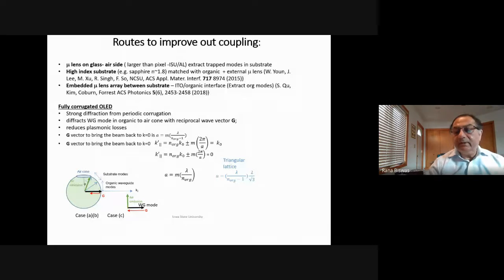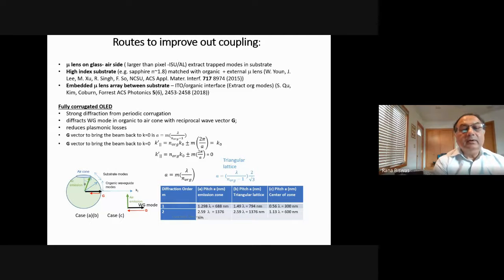So the basic idea is to provide strong diffraction and diffract the substrate modes and the waveguide modes back into the air cone. So that is done by using the reciprocal lattice vector of the periodic array, and it brings these waveguide modes back into the air cone, which then can be emitted into the air.